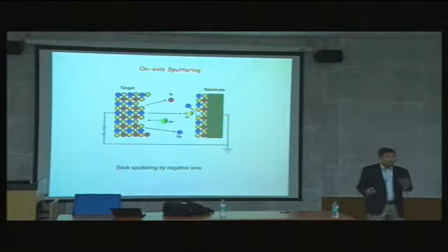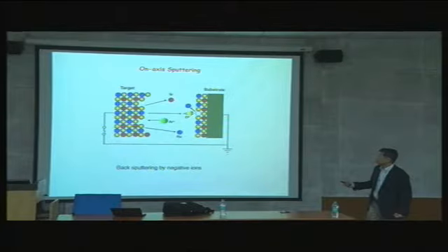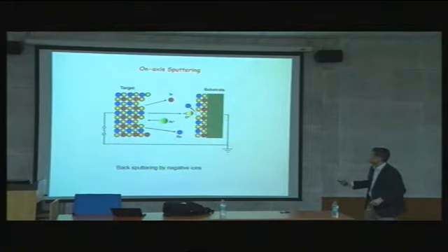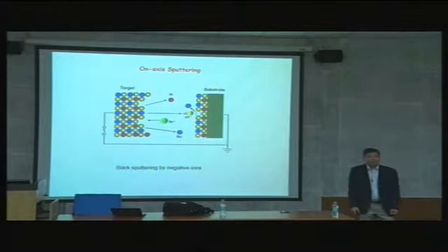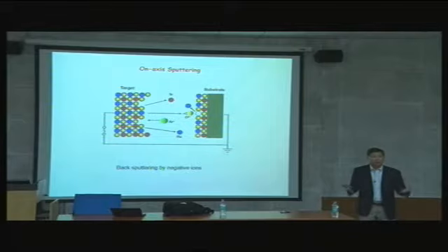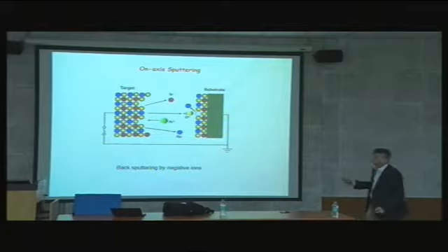But another problem is that this negative bias accelerates these oxygen ions to very high energy. So you have a few hundred eV of energy accelerating this oxygen ion into the material that was already deposited. You know what happened? This is my experience initially. I grew these thin films and ended up with nothing. What I got was just etching of the material, etching of the substrate.